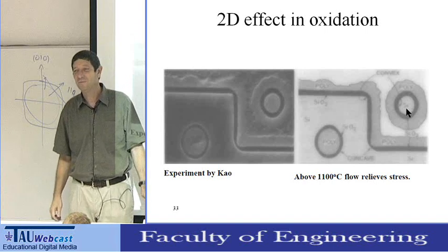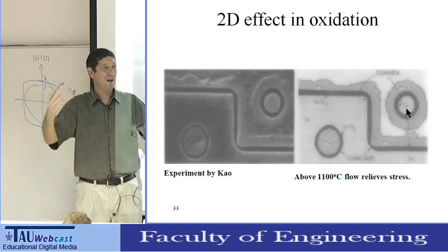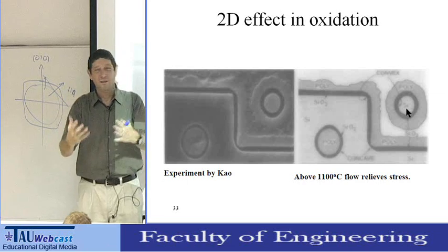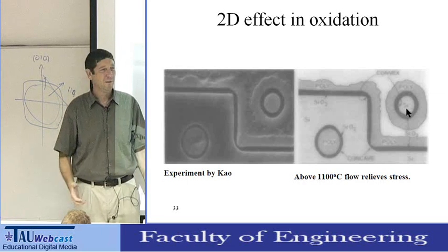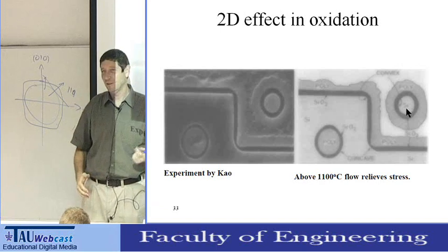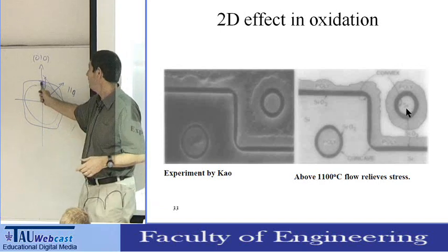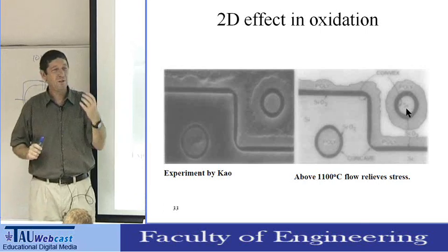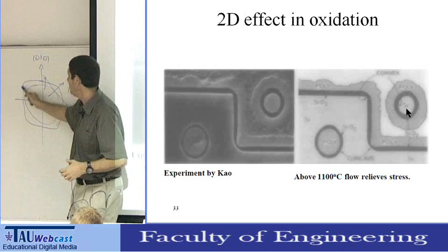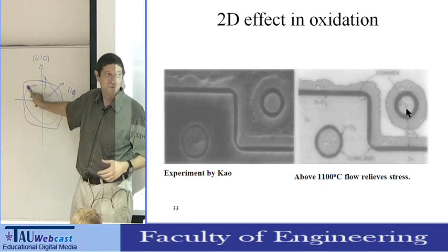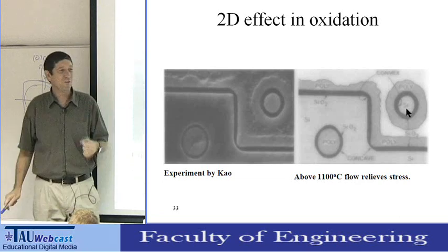If I have a chemical reaction, and I apply something that changes this reaction, what will happen? The reaction will go in a direction to reduce this effect. So if there are areas which generate more stress, and in the corners I will generate more stress, then the reaction rate on the sides will be slower because of the Le Chatelier principle.